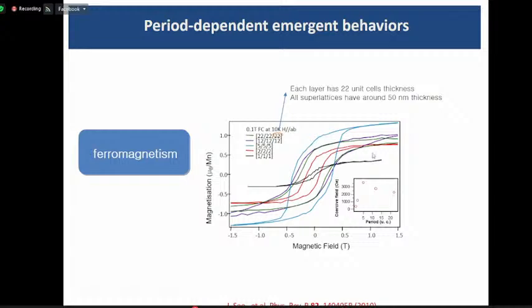So this graph shows that, depending on the period, the coercive field goes up and goes down like this. So this kind of material shows some critical thickness. In the case of around 5 unit cell, they show the peak of magnetization and others as well. So we can see the critical thickness is around 5 unit cell.